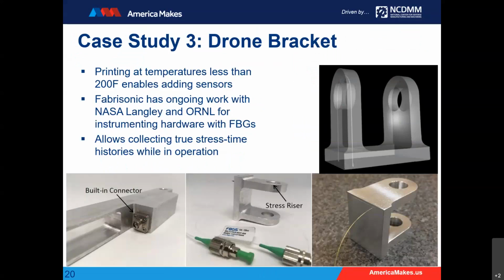Another example also from NASA Langley was a bracket for a drone. As you can imagine, testing 3D printed parts on real flight hardware is not trivial, but testing hardware on a drone is pretty easy to do. So we printed a bracket and a strut from a drone, and we're able to collect true strain time histories of those components while they were functioning. And this gets to the idea of health monitoring. If you can get true strain data from your parts in service, you can better extrapolate life, inspections, and the overall health of the system. So this is an area of active interest for us commercially.